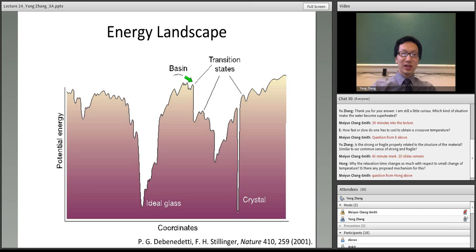For example, for the strong material, the activation energy is basically constant, corresponding to the jumps between all these small basins. For fragile material, the activation energy increases as the temperature is lowered. This corresponds to the transition between these mega basins. In other words, the transition between mega basins corresponds to the alpha relaxation, and transitions within those small basins correspond to beta relaxations.